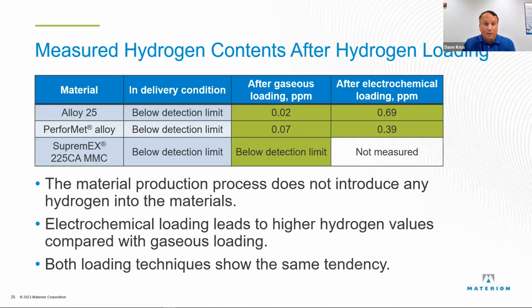And getting to the heart of the matter here is that in the delivered condition, all three of these alloys at TDS didn't show any hydrogen. You couldn't find it. So we're not putting hydrogen into them in the fabrication of them. With the gas loading, those are still very small numbers. They're not absorbing a lot of hydrogen. That's 0.02 parts per million. So put 6 zeros on the other end of that thing. And the Supremex was below the detection limit.